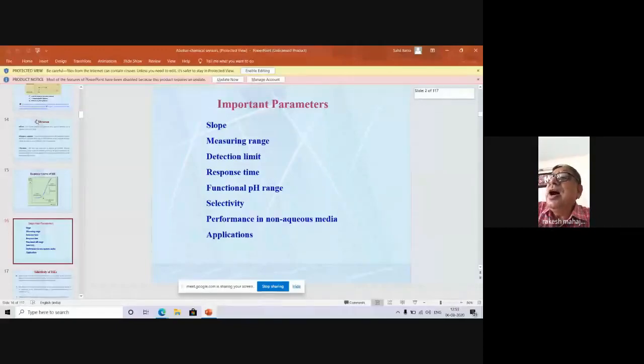Important parameters are needed to see that the membrane is working properly or not. Slope is the first thing which we have already spoken about. That slope should be, for a 1 electron system, 59 millivolts, which you can get from the calibration curve. The measuring range should be very wide, maybe from 10 raised to the power -6 molar to 10 raised to -1 molar, something like that. Detection limit should be low.